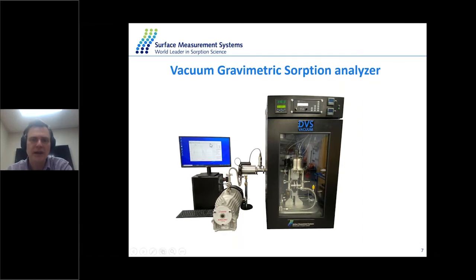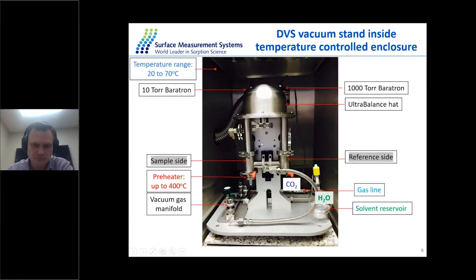There is no limit. There are some limits in terms of toxicity and corrosivity, how corrosive materials can be, so it can damage the pumps. So if you open the door, you can see clearly this vacuum stand made of stainless steel. And under the hood, you have the balance. On the left-hand side is the sample, on the right is the reference side, so it is a true symmetrical balance. Around the sample side, we have a high temperature preheater, which allows us to heat up the sample up to 400 degrees. And then we have two mass flow controllers for delivering vapors and gases.